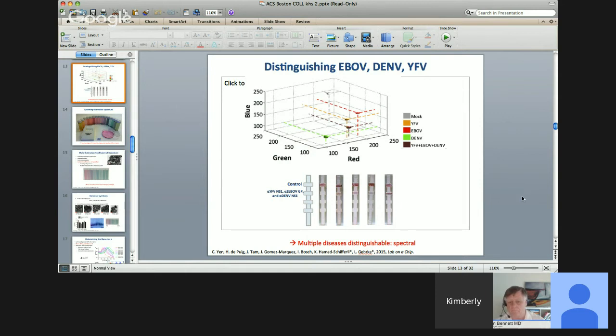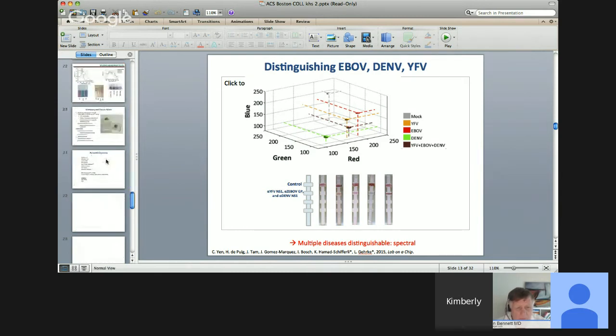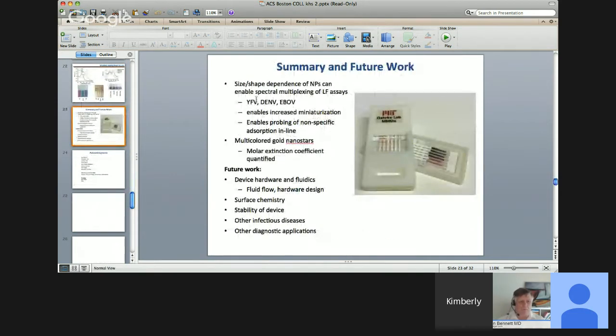And so that's basically what we set out to do. To summarize, what we're able to do is to use the size and shape dependence of nanoparticles to enable differentiation between different diseases: yellow fever, dengue, and Ebola. This can help us increase the miniaturization of these tests, so we can shrink down these test lines and use less and less sample as we introduce it into the device. And it also shows us that there's no non-specific adsorption in the multiplexed line test.